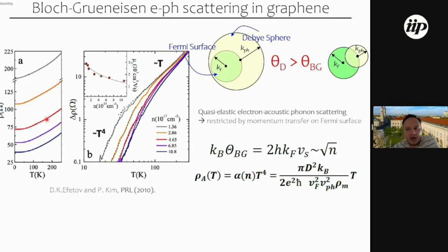And what we find in graphene is that indeed linear temperature dependencies exist. When we analyze our resistance versus temperature curves, there are always, at higher temperature, some regions where we can draw straight lines through the data. However, at lower temperatures, the data becomes a little bit more power law dependent. This is better seen if we subtract the residual resistance and plot it on a log-log scale. Then one can really see a T to the 4, basically a power law dependence at very low temperatures, which goes up to several tens of Kelvin. And above these tens of Kelvin, in the high temperature regime, like at 100 Kelvin, we really observe a linear temperature dependence. This linear temperature dependence is again what we want to distinguish from the strange metal phase.